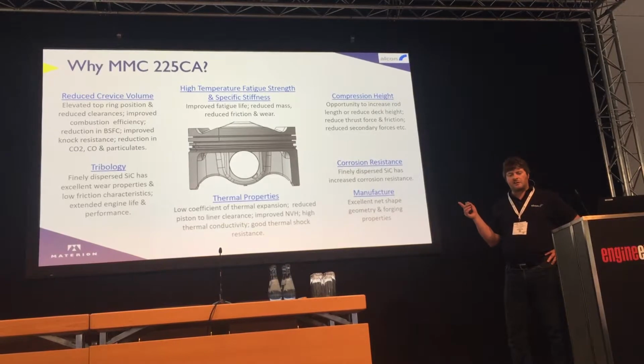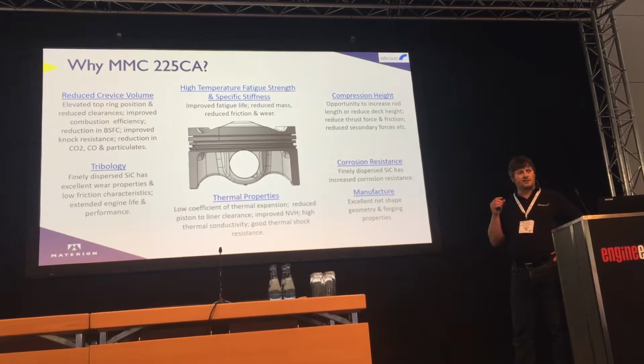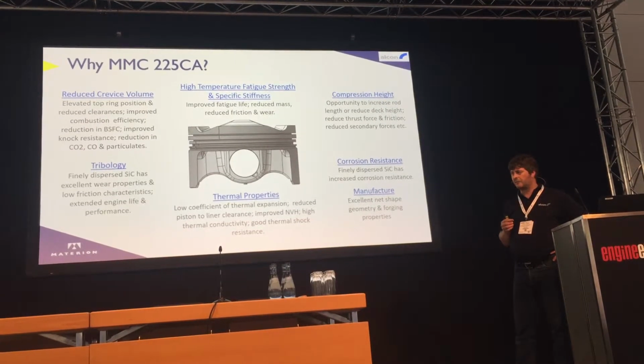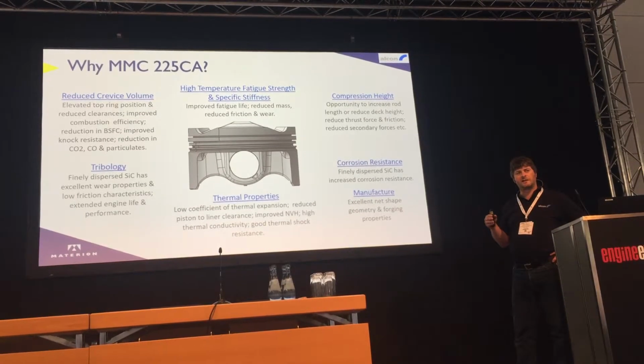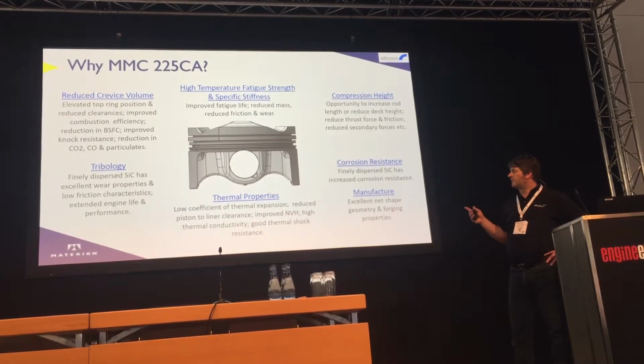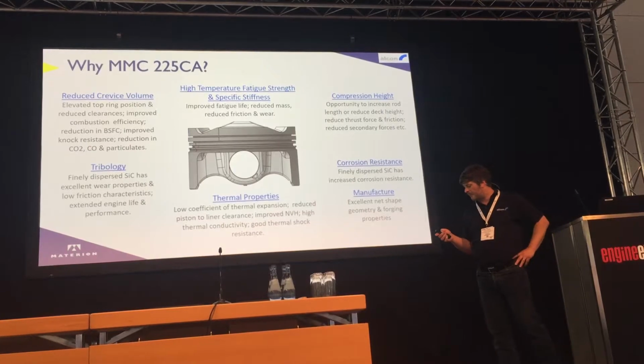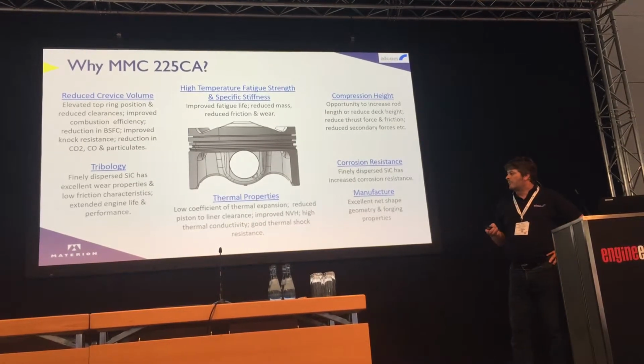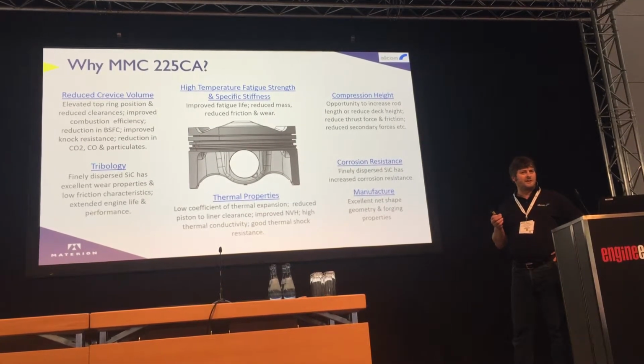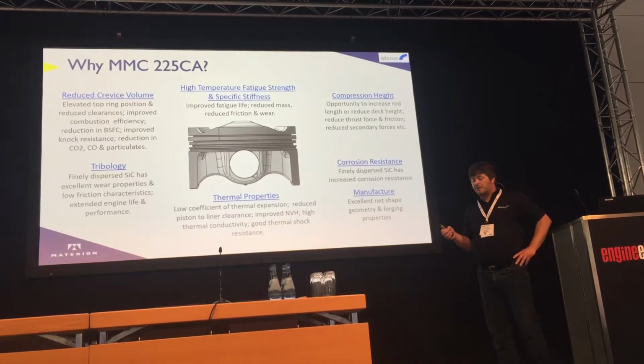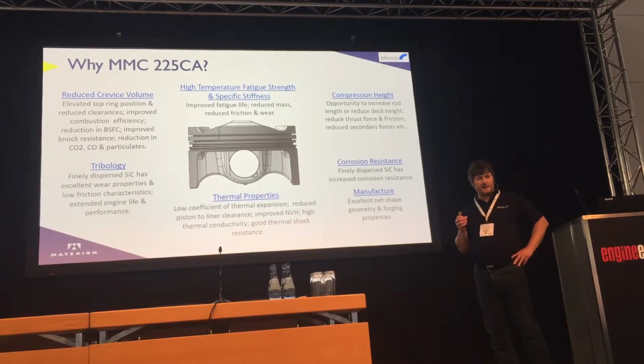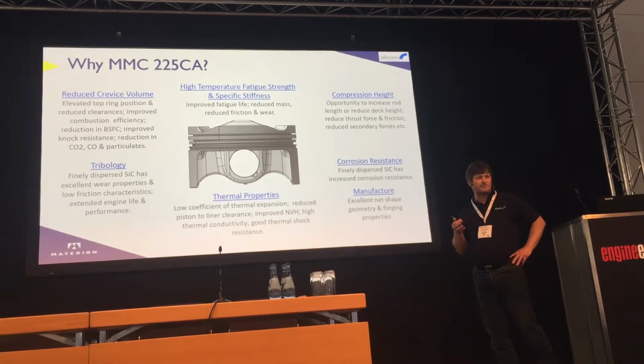So in this particular engine of JLR's, they have a steel ring carrier to protect the top ring groove. We were able to remove that steel ring carrier and also move the top piston ring up. Crevice volume is very important in terms of helping improve combustion efficiency, and we found that it's even more sensitive on boosted engines, basically on very high specific output engines.